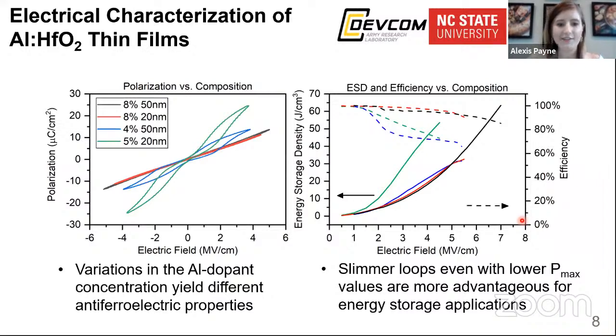So on the left, you can see we have a polarization versus electric field loop. And you can see that the 4 and 5% here have higher max polarization values than that of the 8%. But the 8% has a much thinner, slimmer loop than that of the 4 and 5%.